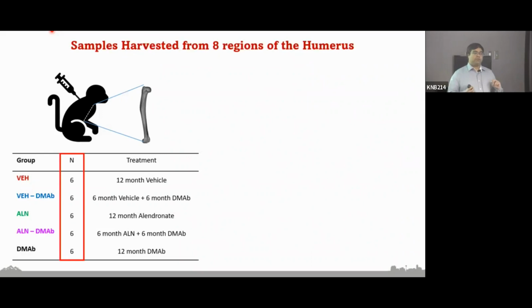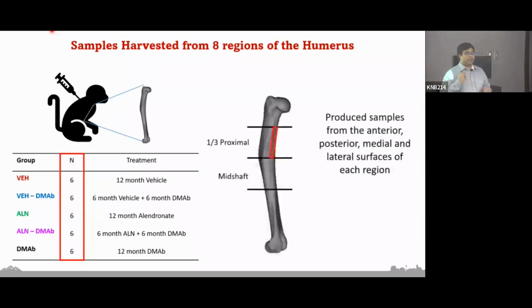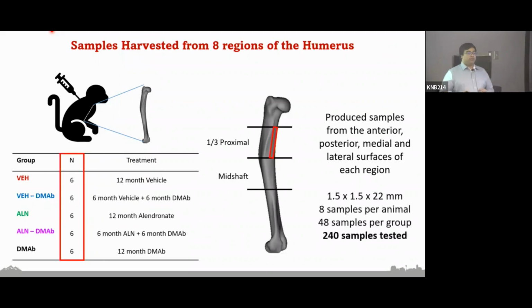In this part of the study, we used a subset of animals so that we could balance all our different loading conditions. Before we were able to test these bones, though, we had to quickly cut up some samples. And when I say we, I mean Andrew Sawatsky, who did all of it. And when I say quickly, I mean that this is very time-consuming, tedious, and challenging work. I think it took him like a year and a half, 2 years or something, Andrew? Yeah. But the reason it took so long is that we were very interested in making sure that things are very uniform so that we had a good test here. We got samples evenly from both the midshaft and the 1/3 proximal region, and we took them from all around the 4 corners of the bone. All in all, across all of our different animals, we had 240 samples that were eventually tested in this study.